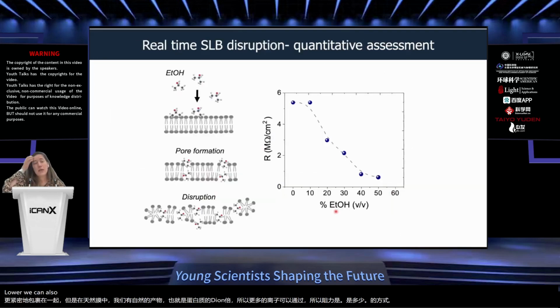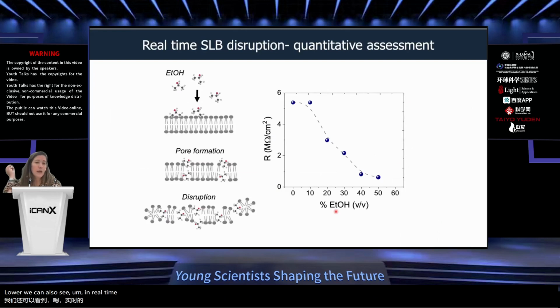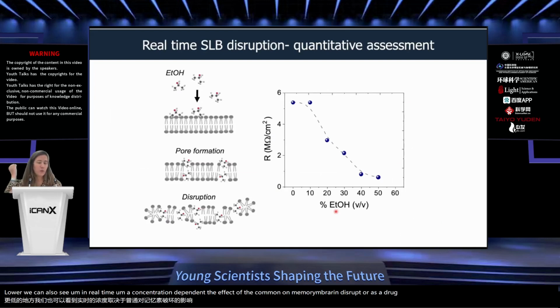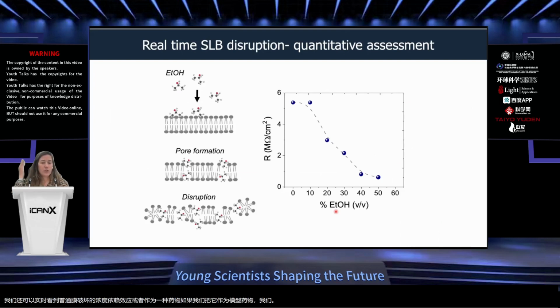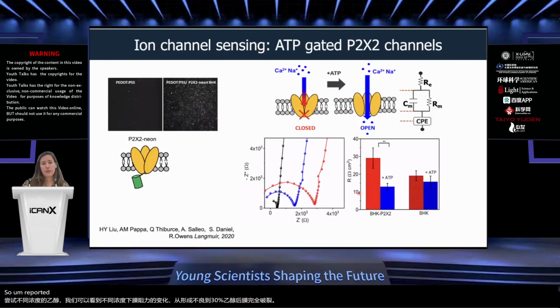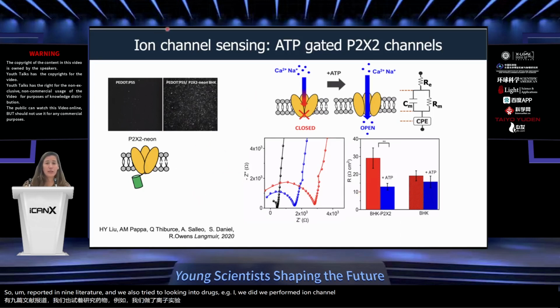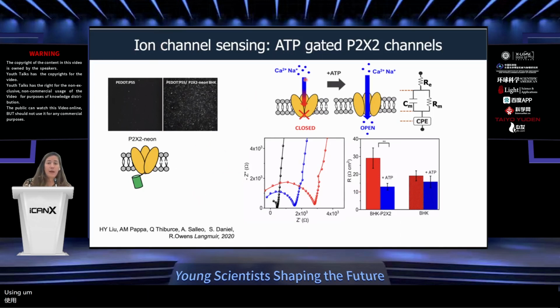We can also see in real time a concentration-dependent effect of a common membrane disruptor, ethanol, which we used as a model drug. We tried different concentrations of ethanol, and we could see changes in the membrane resistance over those different concentrations, from pore formation to total membrane disruption after 30% ethanol, as also reported in the literature. And we also tried to look into drugs. For example, we performed ion channel sensing using ATP-gated P2X2 channels.